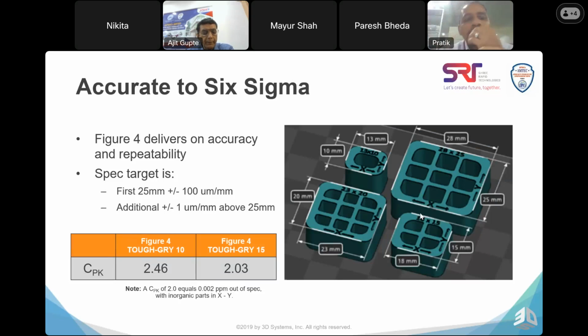Generally you can achieve up to plus or minus 100 microns for the first 25 mm of the dimension. But through our experience, we were able to achieve accuracies of up to 10 to 50 microns plus or minus. That's how accurate the Figure 4 printing is. And you can see some figures here for a specific tough gray resin with a process capability index of 2.46. A CPK of 2 equals 0.002 ppm out of spec. So that's how accurate and repeatable the Figure 4 is.